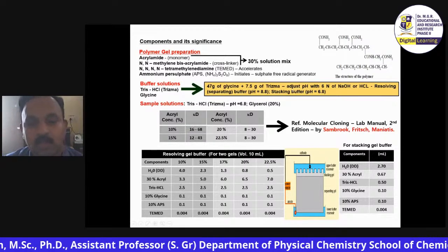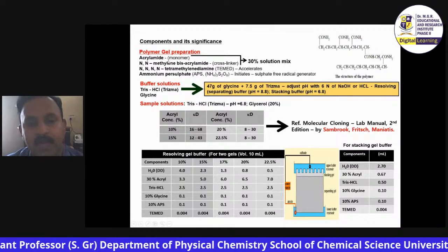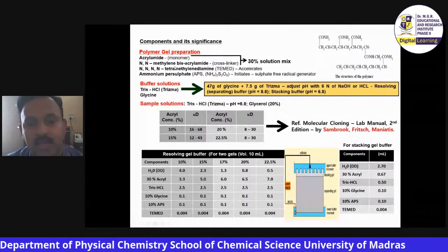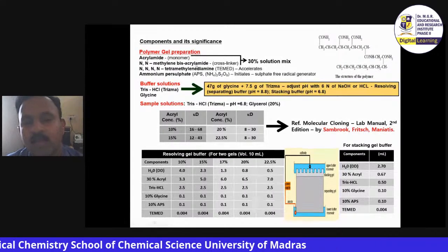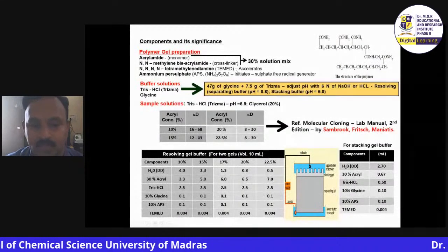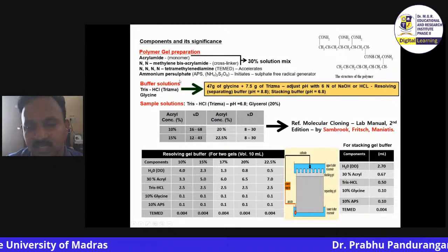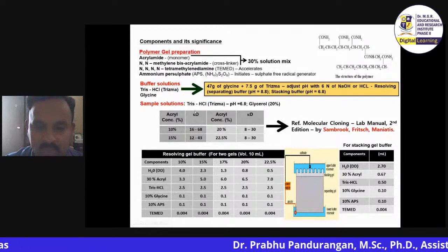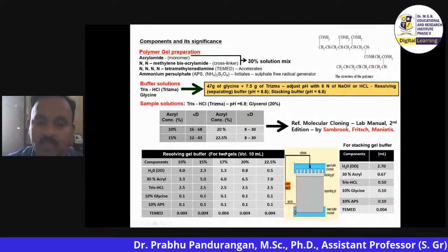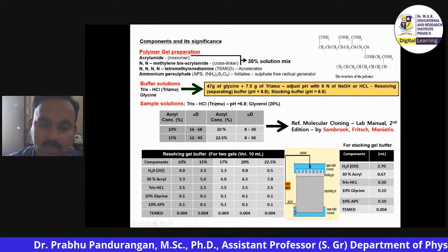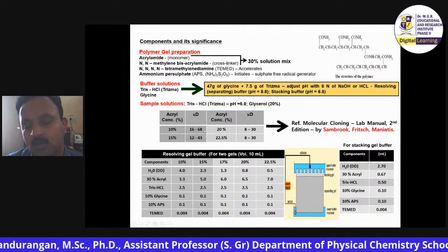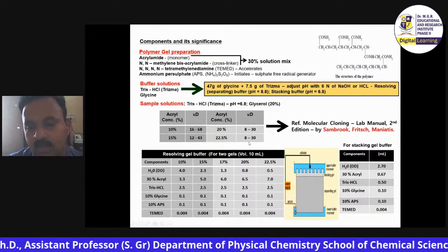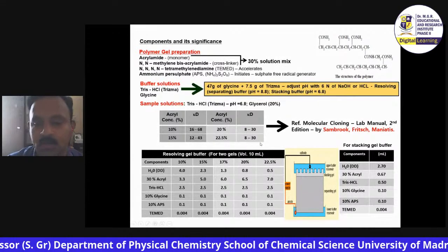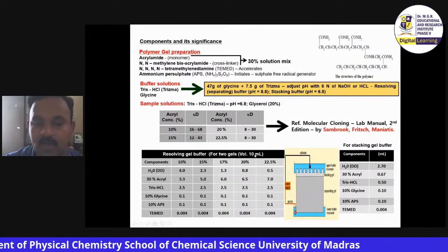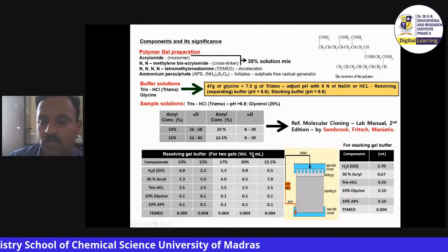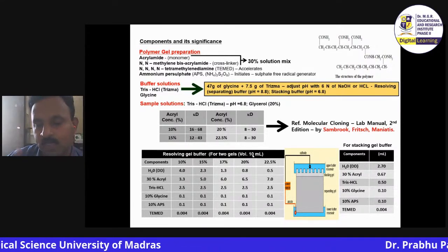The gel which we are making is based on acrylamide, which is the monomer, and we use a cross-linker, methylene bisacrylamide, and we have two other important things, TEMED and APS, ammonium persulfate, which initiates the polymerization. Depending upon the percentage of this polymer gel you are making, the size will vary. You can see here for 10% it is 16,000 Dalton to 68,000 Dalton, whereas for 22.5%, it is 8,000 to 30,000 Dalton. As the percentage is higher, the pore size of the gel will be smaller. So pore size will decide what type of particle you can separate.